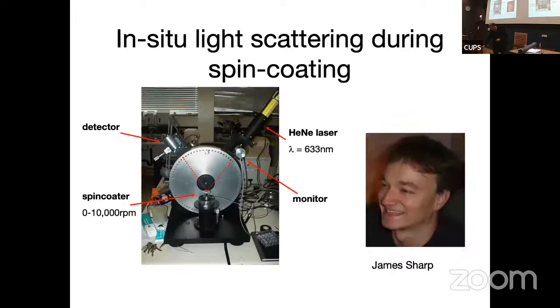So I was interested in how this might work, so I wanted to see what's going on. So what we did was built a piece of equipment that would allow us to study the formation of these films actually as you make them. So in all kinds of areas where you want to make a thin polymer film, for example making photoresists to do lithography, or a thin film of semiconducting polymers to make a light emitting diode or a field effect transistor or a photovoltaic, a very classic way of making a thin film is called spin coating. So you just have a little wheel that whirls around, you just plodge the solution on the top, the solution is spun off, and a very thin uniform layer is left.